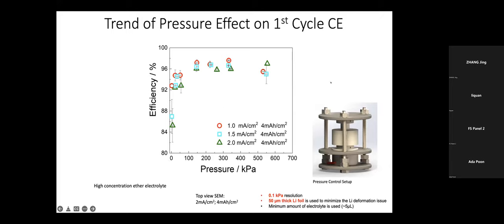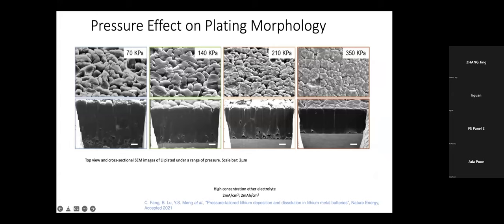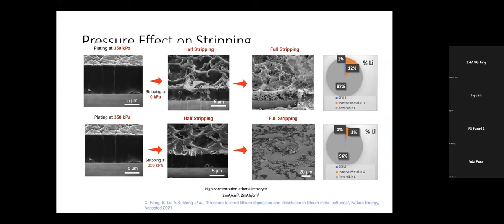And this is clearly demonstrated in our experiment that showcases the importance of stack pressure. Under any current densities, you have a very nice correlation showing around 300 to 400 kilopascal in the liquid cell. Lithium metal needs certain pressure to actually have those densely packed lithium being deposited. And this effect is even more important when you start to strip the lithium metal. So for lithium stripping, you can see that if I start with the same dense lithium, if you don't put a pressure on it, in the stripping you will have actually a very high percentage of inefficiencies.